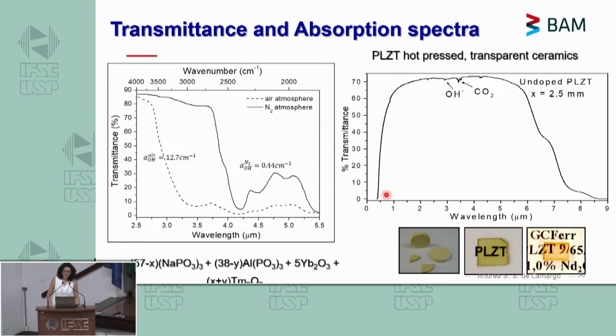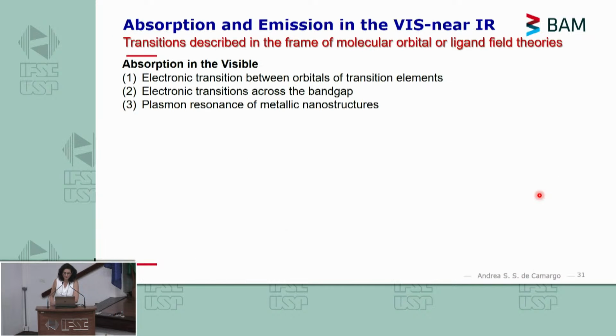And this is actually a ceramic here that was sintered. This was part of my PhD work, so a long time ago. I was working on PLZT, hot press, the transparent ceramics. And we were able here to measure the whole optical window, the transmittance from the UV to the infrared, as you can see. And this particular sample, which was the best one I could obtain, was about 70% transmittance for a 2.5 millimeter sample with this very good transmission window.